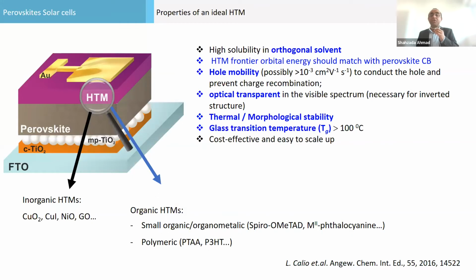But if you want to use them in a perovskite, we have some requirements. First and foremost, it should be soluble in an orthogonal solvent, and the energy level should be aligned with the perovskite, with slight band bending there. And hole mobility should be 10 to the power minus 3 centimeter squared per volt second or close, as with spiro. If this can be achieved without doping, then it's an advantage, because doping is a trade-off between performance and stability. It should be optically transparent for those who work on a PIN structure or tandem devices, so that it doesn't absorb more light. Thermal and morphological stability: glass transition temperature not less than 100 centigrade.